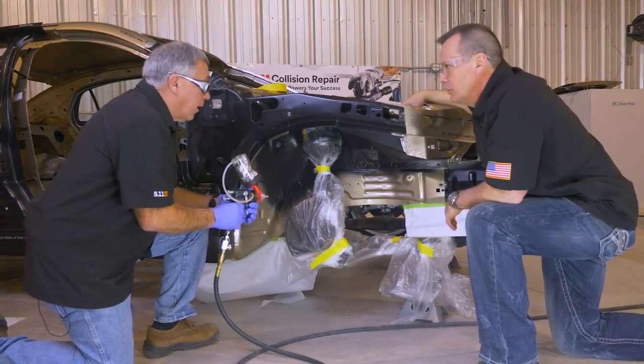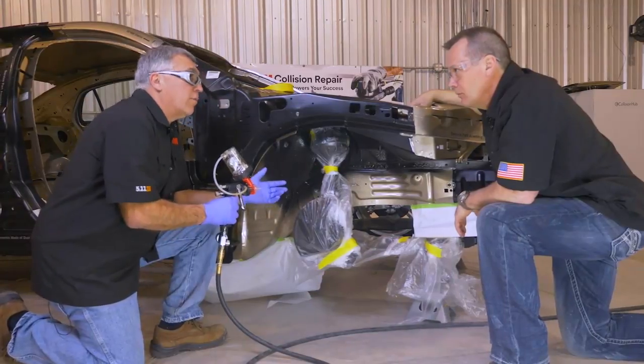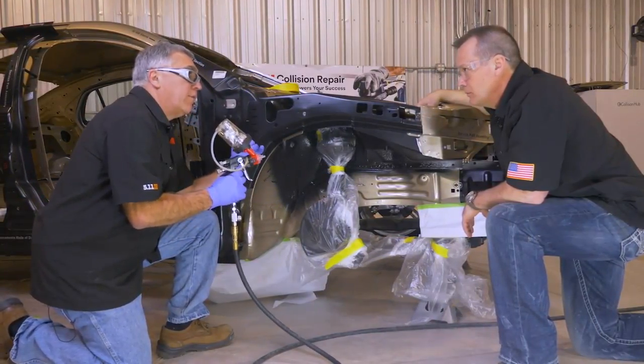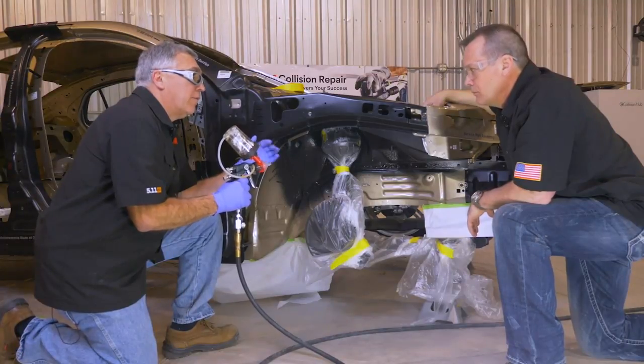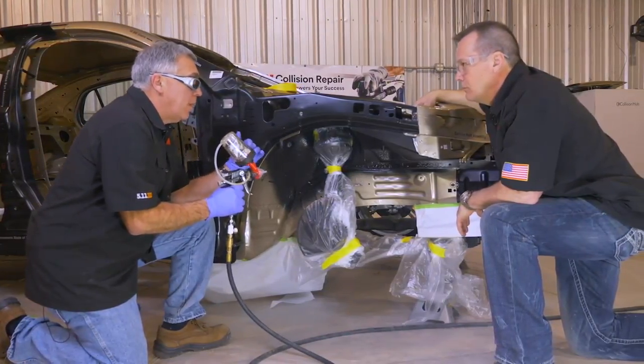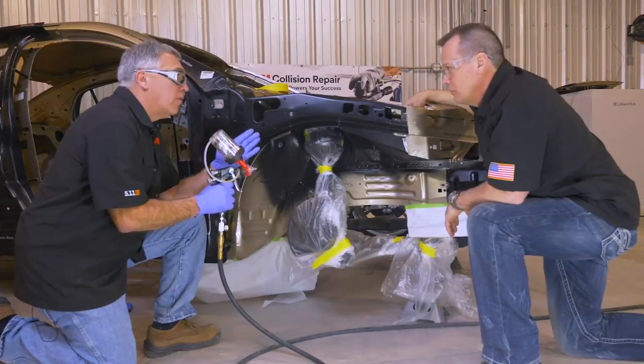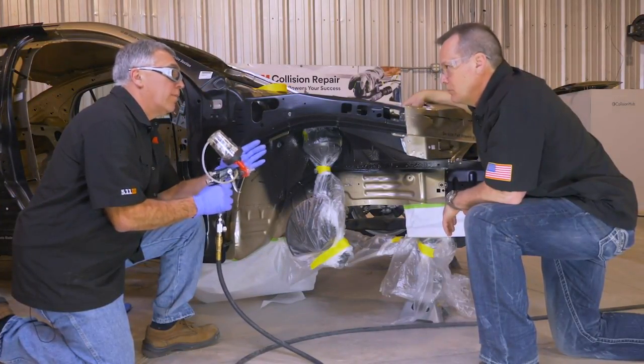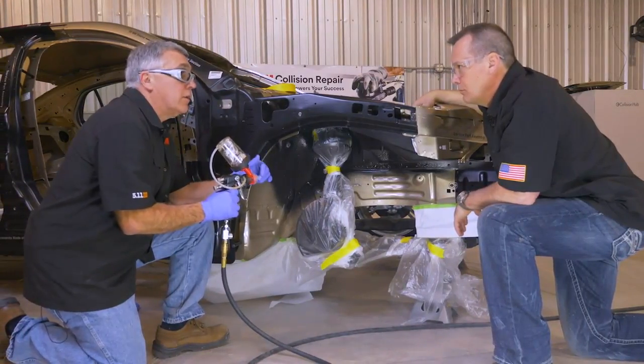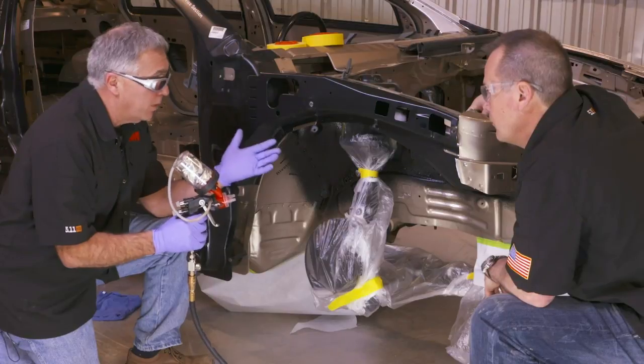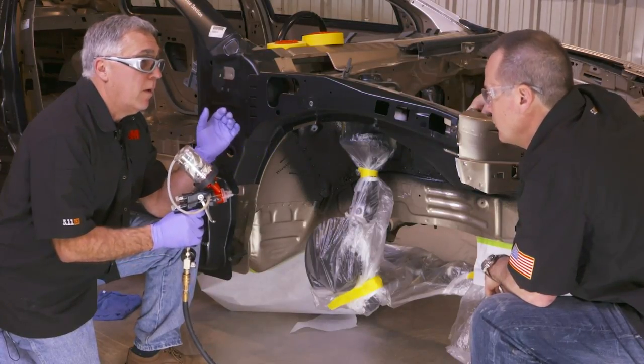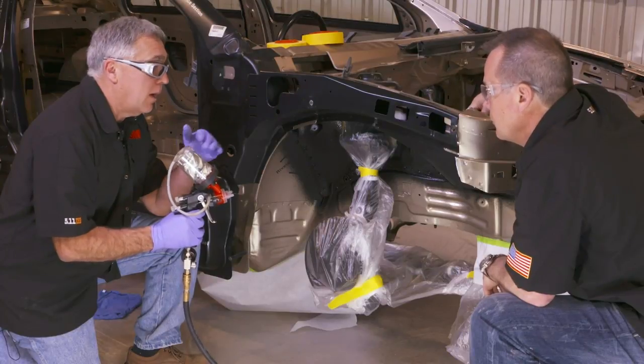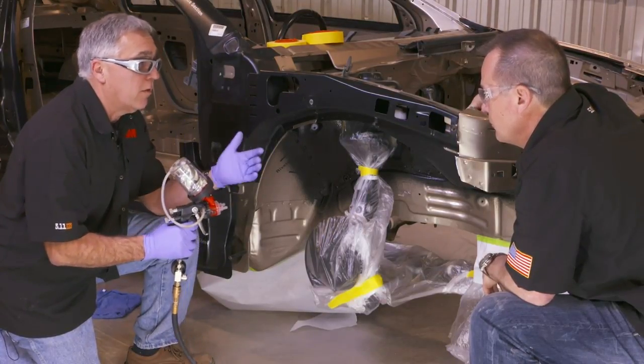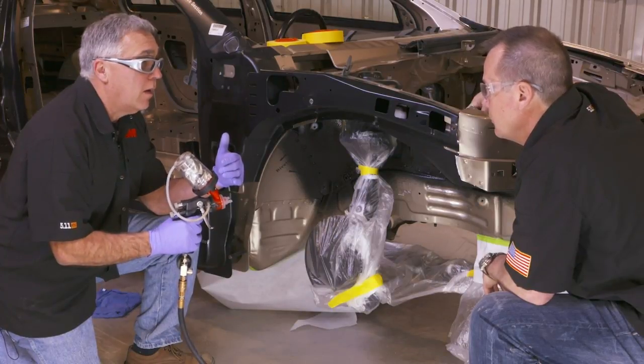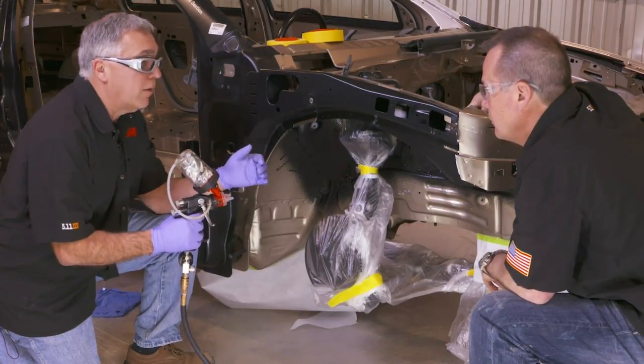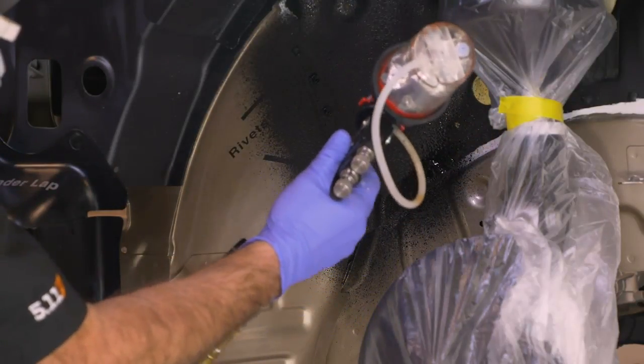Why so many coats? That's a great question. I've seen lots and lots of salt spray tests where we looked at kind of a breaking point for where things were going to be able to prevent corrosion after 1,500 hours. And it always seemed like a dry mil thickness around 10 or slightly above 10 mils was going to give you the protection you really needed under really harsh conditions. And so this type of material, believe it or not, has about a 50% shrink rate from a wet mil thickness to a dry mil thickness. I've seen that across many different products related to undercoating. So it's not just this particular one, but in general, that's a rule of thumb. And so we found if you put 4 coats on, it's going to give you 20 plus mils.